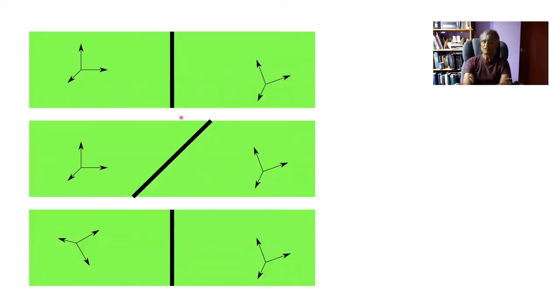So this is an illustration of how these 5 degrees of freedom matter. So here we have two crystals in different orientation. These are the unit cell axes, and this is the interface plane. Recall the 5 degrees of freedom, because we can change them independently. So for example, I can change the orientation of the interface without changing the relative orientations of the crystals. So obviously I've changed the orientation of the interface plane, but the crystallographic orientations of the bicrystal are exactly the same. Alternatively, I can go from here to here, maintaining the interface plane constant, but changing the relative orientations of these two crystals.